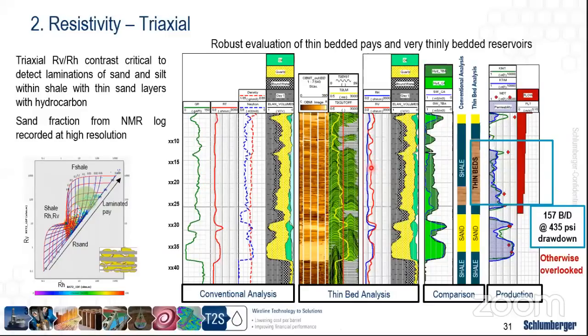And when they were tested, this came out to be producible, and it added another pay zone that was previously missed just due to the fact that we were just relying on the RT itself. So in this case, the major sand body was already identified by the conventional laterolog, which is RT. But using the RV and RH, using the triaxial resistivity, we're able to add more pay into the reservoir through the thin bed laminations that were evident initially on NMR and images, and they were backed up by the RV when the RV and RH computation was done.